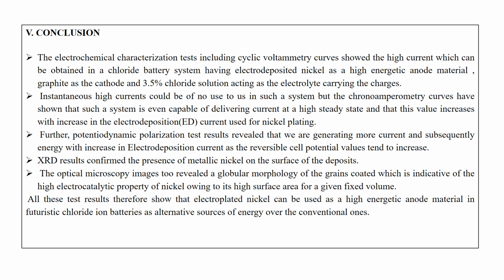Even the XRD results confirm the presence of metallic nickel on the surface of the deposits, and the optical microscopy images showed the globular morphology, which is indicative of the high electrocatalytic property of nickel. So all the results show that electroplated nickel can be used as a high energetic anode material in futuristic chloride ion batteries, and can be used as an alternative source of energy over the conventional ones. Thank you.